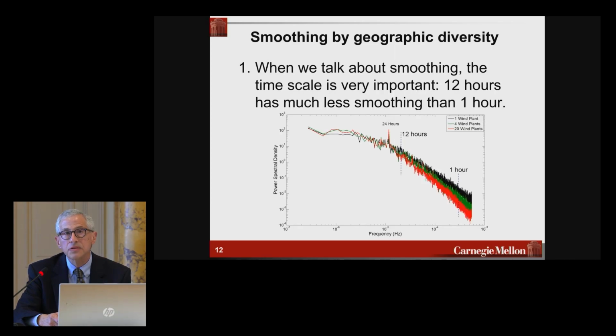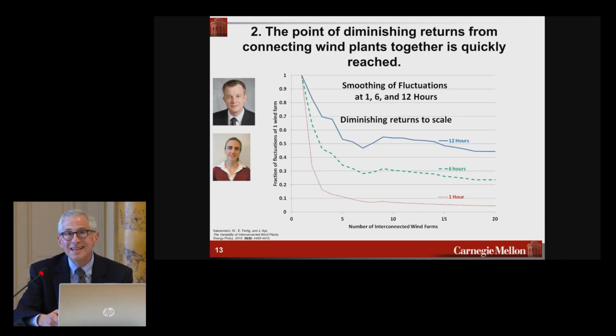What we've learned are 2 basic things about smoothing by geographic diversity from looking at the physics here. The first is when we talk about smoothing, the time scale is very important. As I mentioned, 12 hours has a whole lot less smoothing than an hour. At 12 hours, we smooth about half of the fluctuations. At an hour, we smooth about 95% of the fluctuations. The second is the point of diminishing returns from connecting wind plants together is very quickly reached. You get almost to the asymptote after about a half a dozen wind plants are added together.